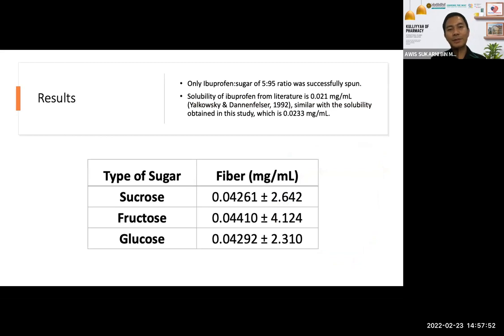From the result, we tried to increase the drug to sugar ratio for these 3, but the only ratio that we managed to spin is just 5% ibuprofen. So we proceeded with 5% ibuprofen, and then we did the solubility test on the pure ibuprofen. We got the solubility of the pure ibuprofen as 0.0233 milligram per mil, which is similar to the other study, which is 0.021 milligram per mil.